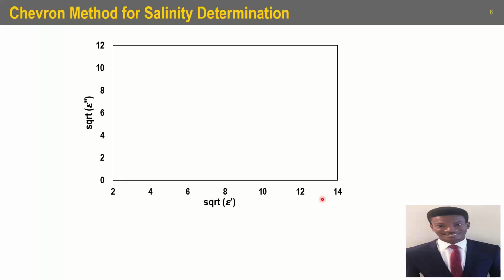The next method that we have is the Chevron method for salinity determination. So Chevron developed this method based on the square root of the relative permittivity and the square root of the dielectric loss on brine of known concentrations to determine the calibration curve that is shown on the right here. So from the relative permittivity and dielectric loss values on bulk brine solutions, we can determine this calibration